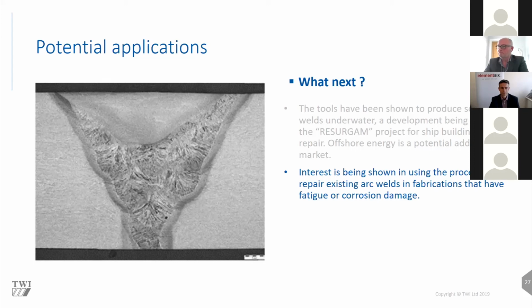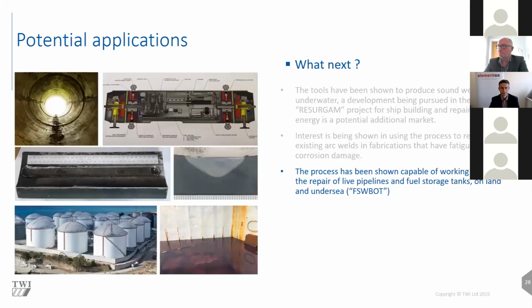We then ran a friction stir welding tool through the cap of that weld, and that has returned that large columnar grain structure back to a very, very fine grained wrought structure, very similar to the parent material. And so it's perhaps not surprising that we're seeing the friction stir weld having very good properties, at least as good as the parent material. And so that's been looked at as a technique for repairing welds.